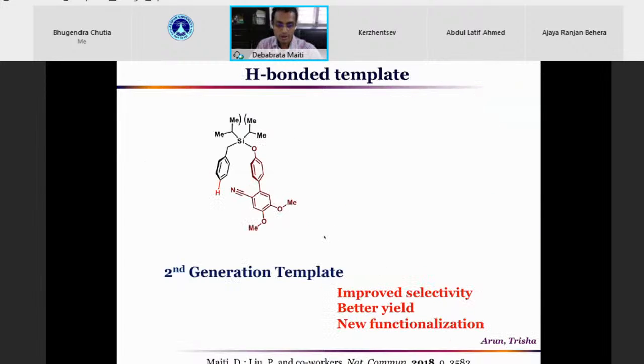Okay, moving on. Well, of course, one of the problems was we could not do the functionalization very efficiently without this dimethoxy group, and there are a number of problems if we substitute things at any other position. Very recently, we were able to show that by having this dimethoxy substituent, we can get a second generation template which is going to be much better in terms of selectivity, yield, and functionalization.